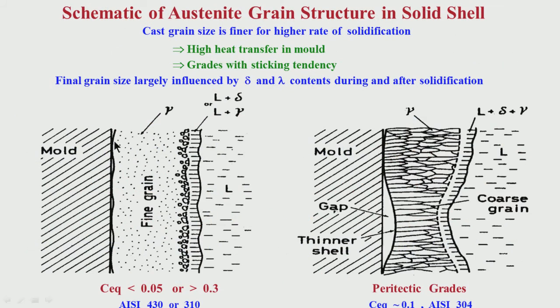If you have a sticking tendency, that means this solid shell is going to try to touch the mold surface. In between you have a thin layer of molten powder, that means mold slag. So, the mold slag characteristic has to be such that the friction between the mold and the solid shell is relatively less. Because sticking tendency means the friction will be relatively high. So, the characteristic of the mold slag has to be such that this high friction can be taken care of.